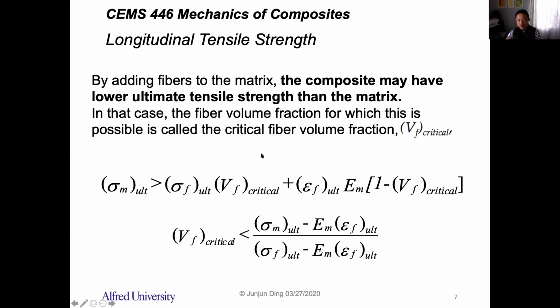So there's a critical volume fraction of the fiber that has to be reached to effectively increase the ultimate strength of the composite. If we compare the ultimate strength of the matrix and the ultimate strength of the composite, right? If the ultimate strength of the matrix is larger than the composite, that is bad. So in this way, we can calculate this critical fiber volume fraction based on this equation.